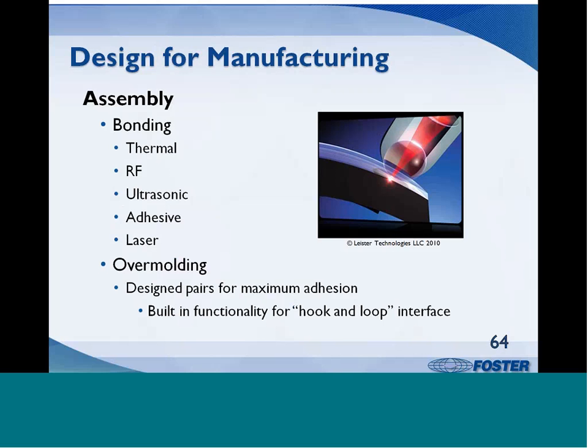The wrong dispersion aids can impact thermal and ultrasonic welding by leaving a waxy residue on the surface. Laser welding can be enhanced with additives and pigments which absorb and concentrate the laser's light energy into heat. Overmolding can be simplified if the base cover system is designed to work together. Additives can go into each resin to create a molecular hook and loop interface.